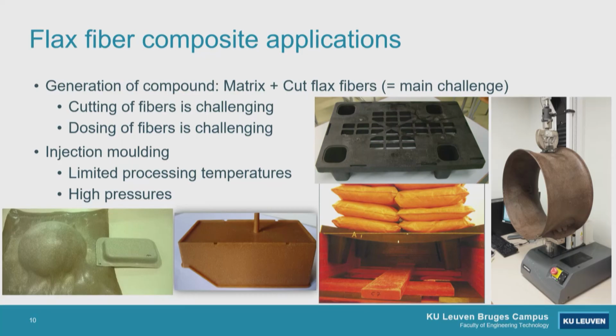Okay, so what's the whole thing? Of course, to generate this compound, we have the matrix, starting from this polyethylene or polyolefins, and to add these cut fibers. So to cut these flax fibers into a controlled length and to get it nicely compounded is indeed really the main challenge. So to cut it is challenging, also the dosing is challenging, because cutting this natural fiber is always a lot of wear on the knives and to cut it in a controlled way.